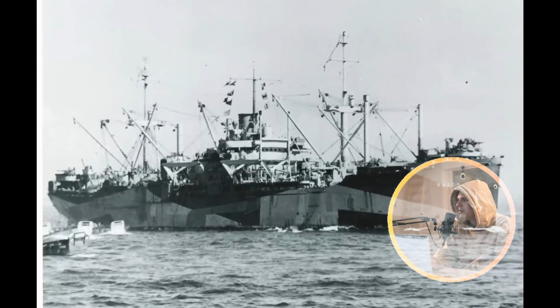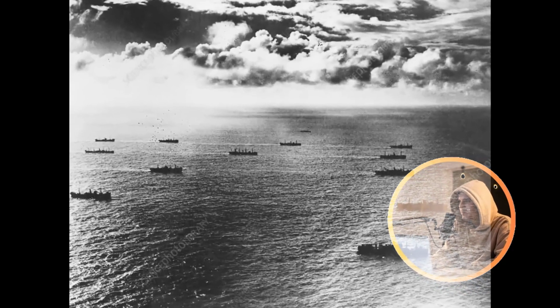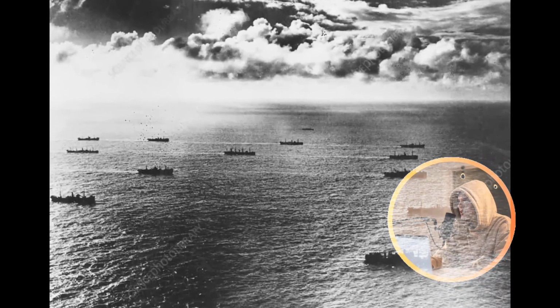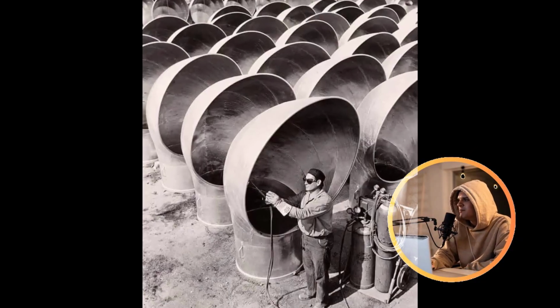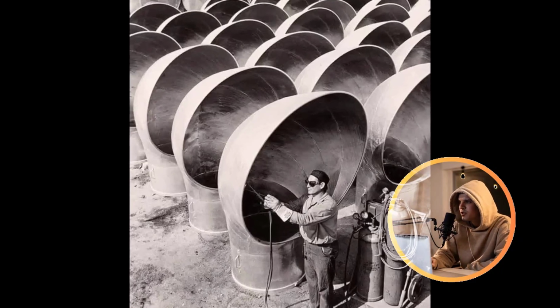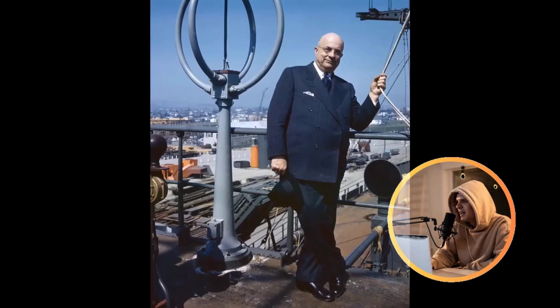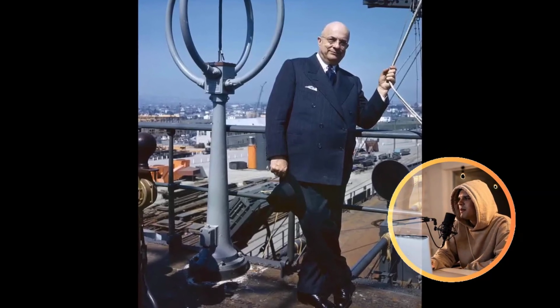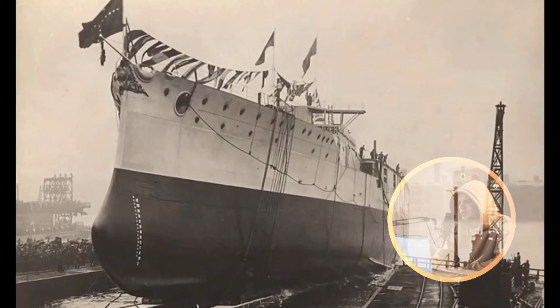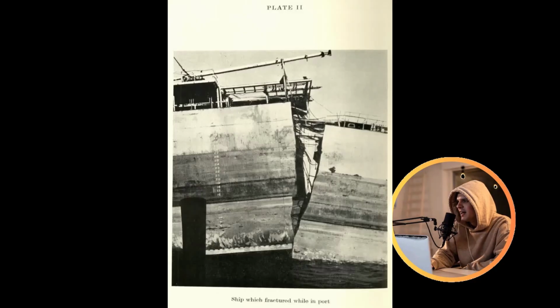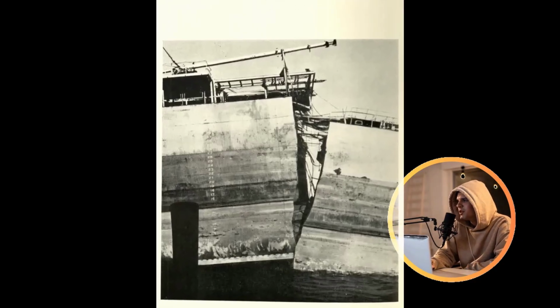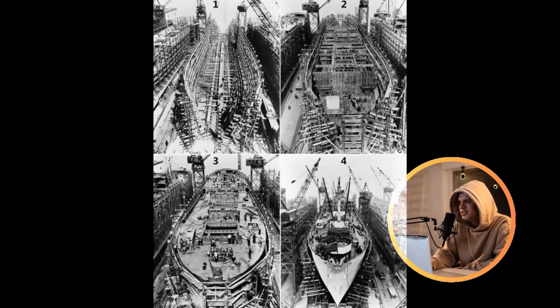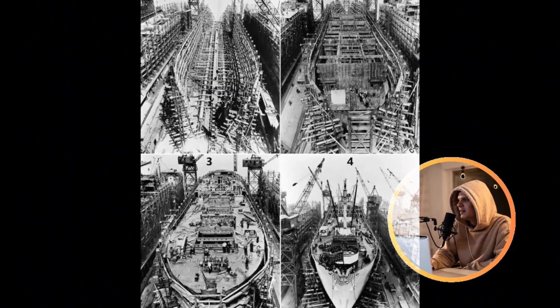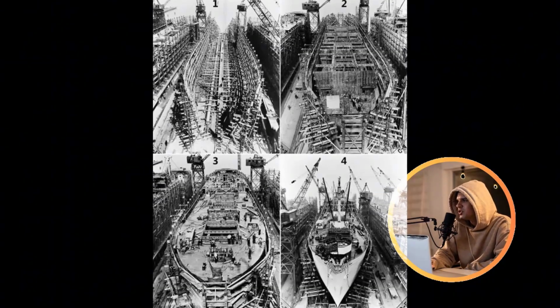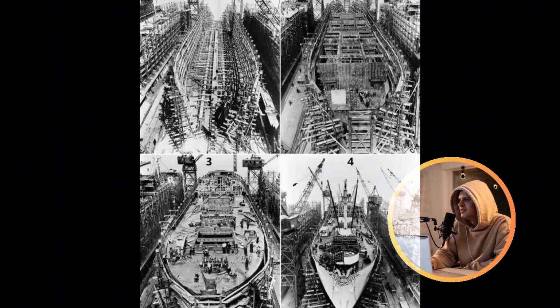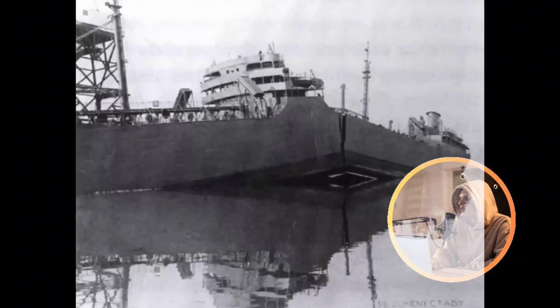The introduction of an improved steel specification proved absolutely pivotal. This innovative alloy, aptly termed killed steel, due to the precise addition of aluminum during its production to effectively remove oxygen, exhibited dramatically enhanced toughness, particularly in frigid temperatures. Extensive laboratory analyses revealed that the critical transition temperature, the precise point at which steel undergoes a perilous transformation from ductile, flexible behavior to brittle, fragile rigidity, had plummeted from approximately 40 degrees Fahrenheit in Liberty ship steel to a mere 5 degrees. This significant 35-degree improvement meant that Victory ships were able to retain their essential structural flexibility and resilience even in environmental conditions that rendered Liberty hulls dangerously fragile and prone to catastrophic failure.